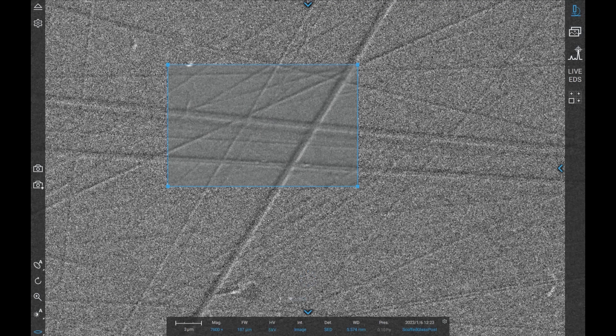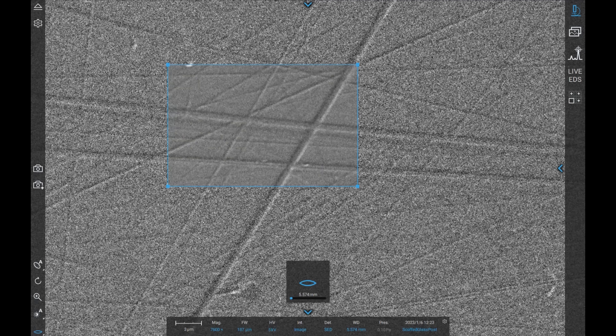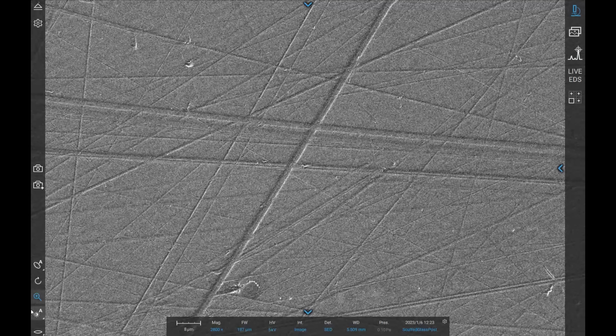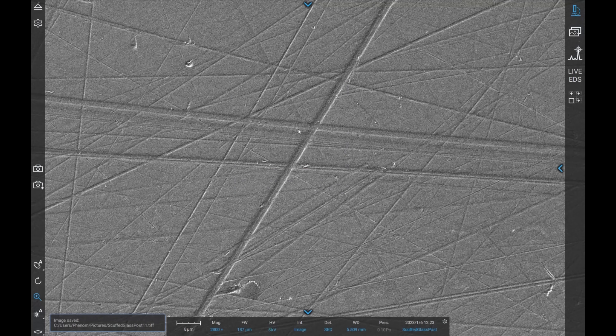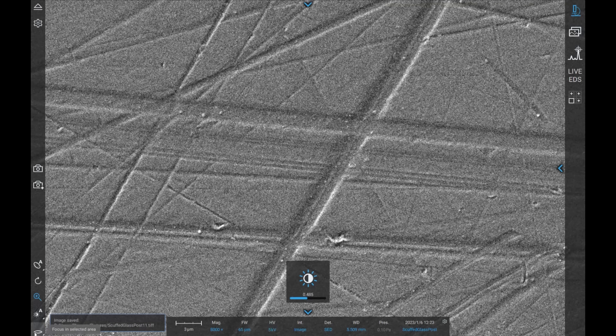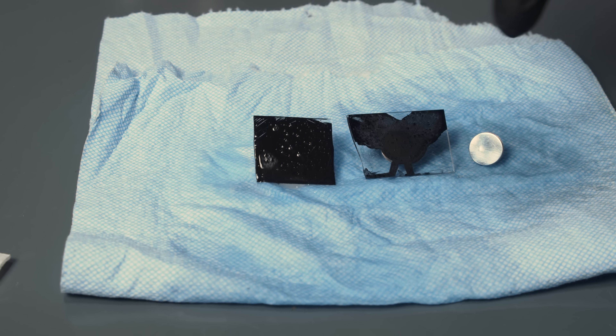Since we're using SEM and just looking visually, we can't quite confirm these are the silica particles — it could be blobs of carnauba wax or PDMS silicones in little particles — but it's likely amorphous silica given the size and shape. Scanning around the test sample, all the scratches seem to have some amount of particles in them, with some particles sitting on the top surface too but generally reserved for the scratches. The viewers who mentioned the substrate being a poor choice — kudos, that was a really good point.